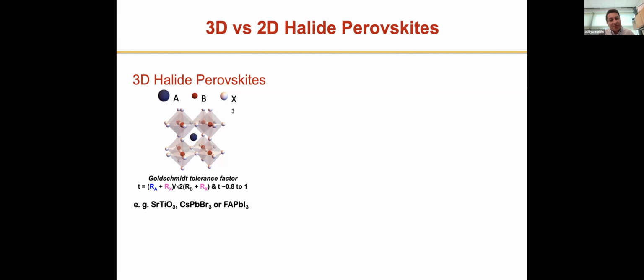And if you get a value between 0.8 and 1, then you've successfully made a three-dimensional perovskite. And so if you're on either of these edges of these numbers, then you don't get a perovskite phase. You may get something different, maybe a polymorph of this, or something that's a different structural phase.